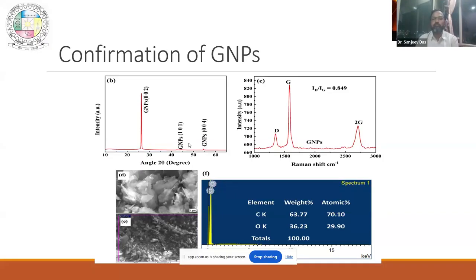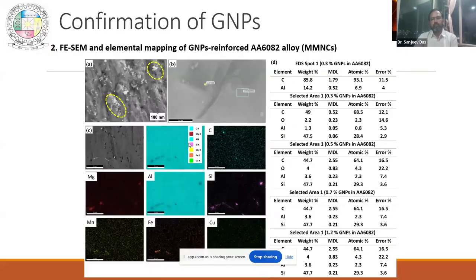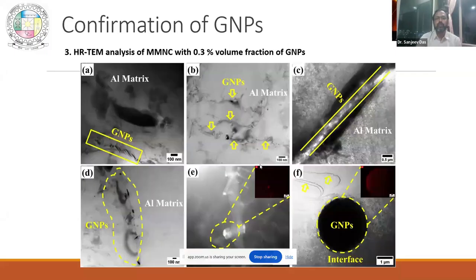So for that we went for transmission electron microscopy. Before that, we did some SEM, and we took some dot mapping. We found that if you see the carbon, you see a lot of dots uniformly distributed. Now the problem with EDAX is it will tell you that yes, carbon is there, but whether this carbon is GNP carbon or not, that confirmation it is not giving. But it is showing that there is a certain distribution of carbon around the matrix.